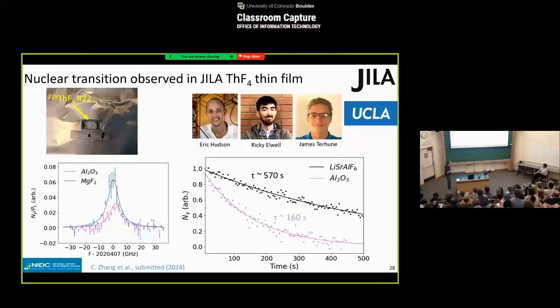So also we have some remaining mystery in these samples. For the bulk crystals, either in our calcium fluoride or in lithium strontium aluminum fluoride grown at UCLA, we all observe a lifetime on the order of about 600 seconds. But in these thin films, we actually observe a much shorter lifetime, about 160 seconds. And we don't fully understand that yet. We have some theories that explain maybe part of it, but there is still more understanding to be gained.